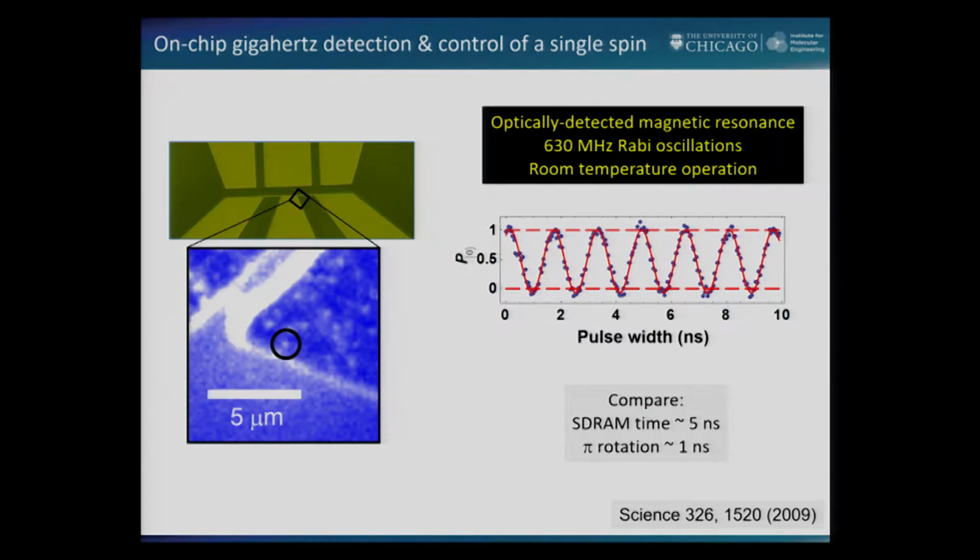And all of this happens in a large band gap. So in many of these materials, such as diamond, doing this in a 5 eV band gap means that many of these processes are robust not just at room temperature, but well above room temperature, up to 600-700 Kelvin. And for sensing applications, that's actually very interesting. And for real applications where materials will be relatively warm, like your laptop, it's nice to know that you can maintain the coherence at higher temperatures.